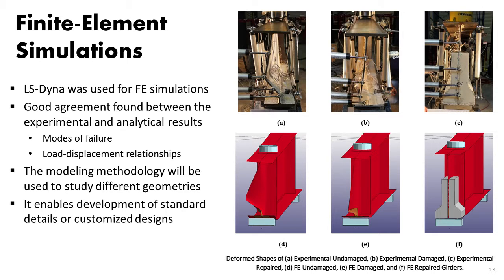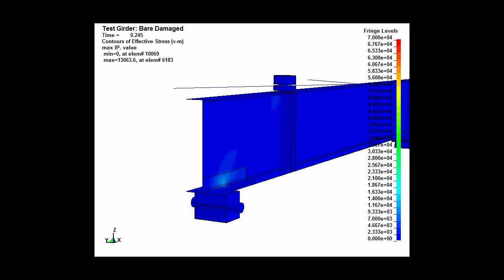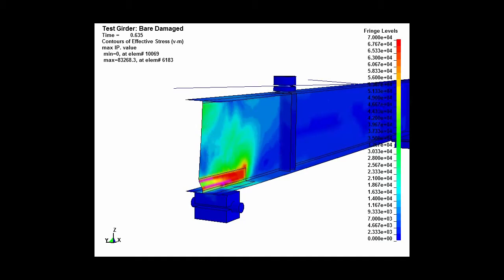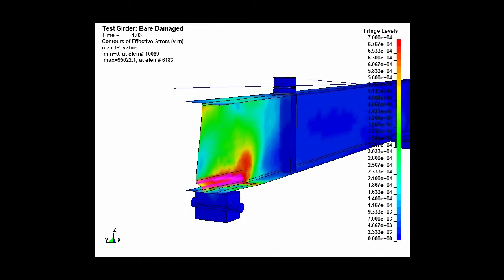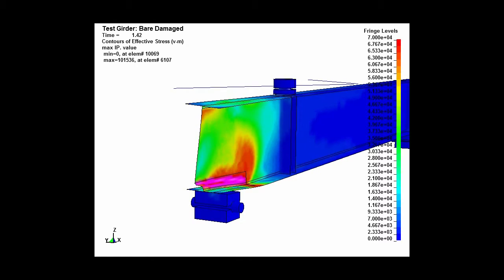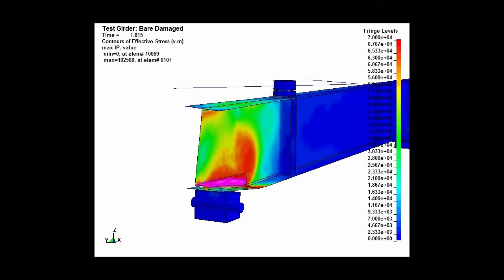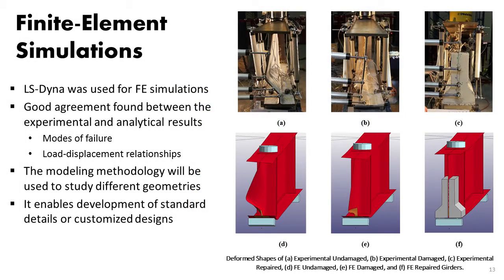We followed up with some finite element simulations. We got very good agreement between our experimental results and finite element modeling. We used LS-DYNA, and you can see here global buckling, almost identical failure pattern. And we developed modeling methodologies for repaired and damaged steel beams. This quick animation shows, for example, how stresses develop and buckling happens, and then all the deformations are localized in that region of the beam. So this finite element modeling allows us to evaluate the in situ capacity of a beam with a certain level of corrosion and also evaluate the effectiveness of our repair.